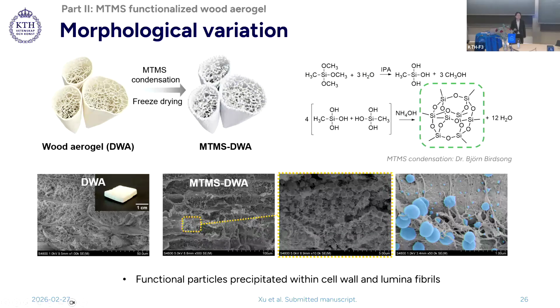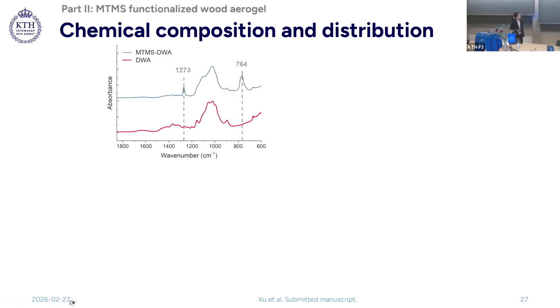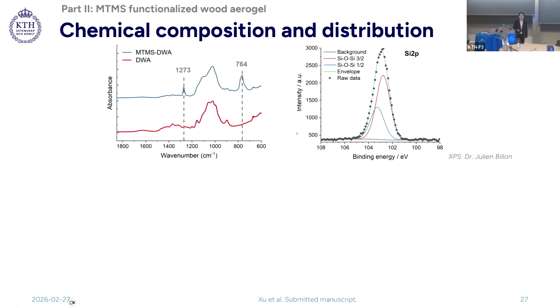To confirm the nature of these particles, chemical analysis was performed. From FTIR, we can see two new distinct peaks, which are associated with silicon. XPS also reveals that the binding energy of the silicon 2p signals is consistent with silicon methyl moieties, indicating the successful coating on wood aerogel.